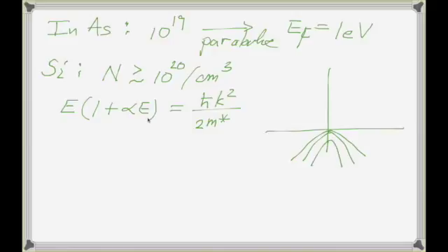But in silicon, here's my pi over A, and I'll only draw half of it, since you've got your minimum real close to the band edge out here, something like this. And so your conduction band edge is way over here, actually at about 0.85 of the way out to the edge of the zone.